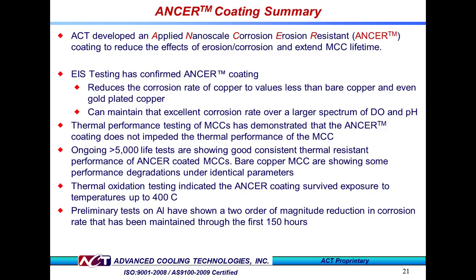So let's do a quick review of what we presented today. The Applied Nanoscale Corrosion Erosion Resistance Coating, ANCER, developed by Advanced Cooling Technologies, can provide superior corrosion erosion protection for copper microchannel coolers. Electrochemical impedance spectroscopy, EIS, showed the ANCER coating reduces the corrosion rate of copper to values less than both copper and gold-plated copper, and can maintain that corrosion rate over a wide range of dissolved oxygen and pH values. Thermal performance testing demonstrated that the ANCER coating does not impede the MCC operation.